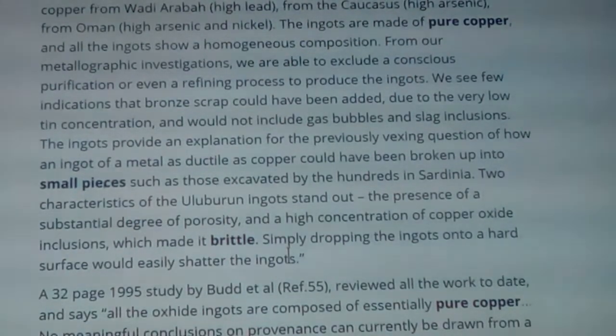From metallographic investigations, we were able to exclude a conscious purification or even a refining process to produce the ingots. We see few indications that bronze scrap would have been added, due to the very low tin concentrations, and it would not include gas bubbles and slag inclusions.